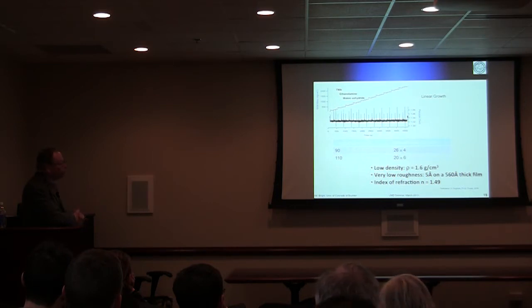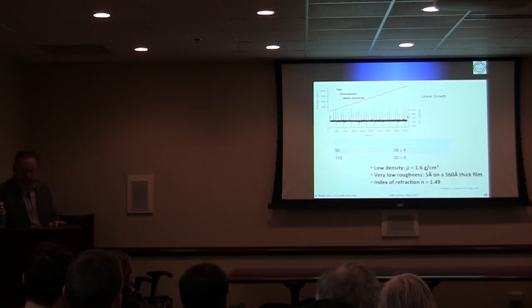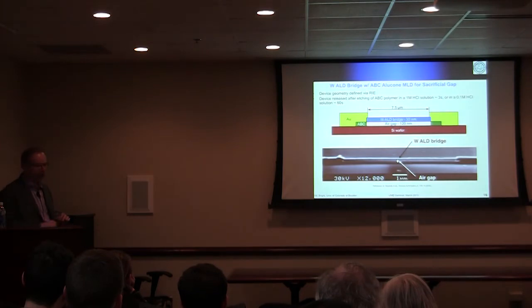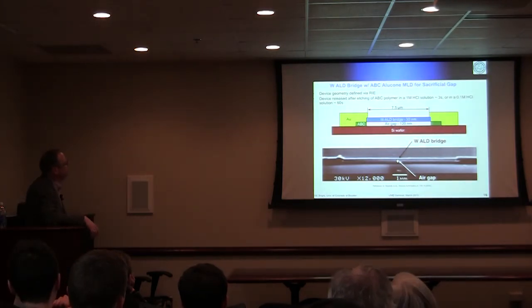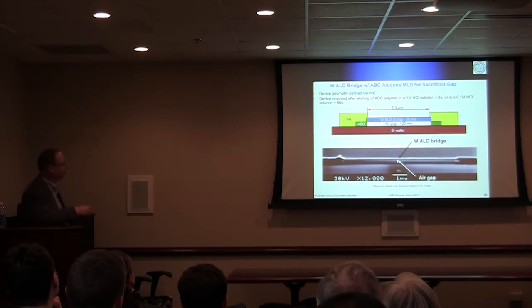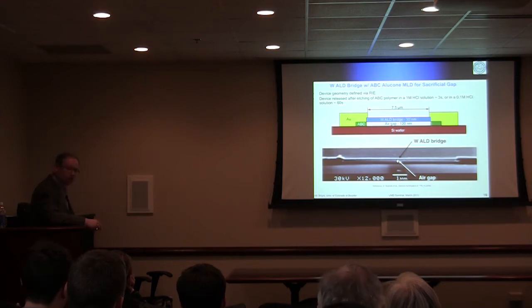But it does produce coatings at a low density, low roughness. And the interesting thing, so you say, well, what's the first application of this? Well, the first application of this was we were using this as a sacrificial layer for making nanostructures. So what you see here is a very simple structure, a tungsten beam suspended. This is done by ALD. And the gap here, this air gap, was actually the alucone MLD coating, which was removed in hydrochloric solution.